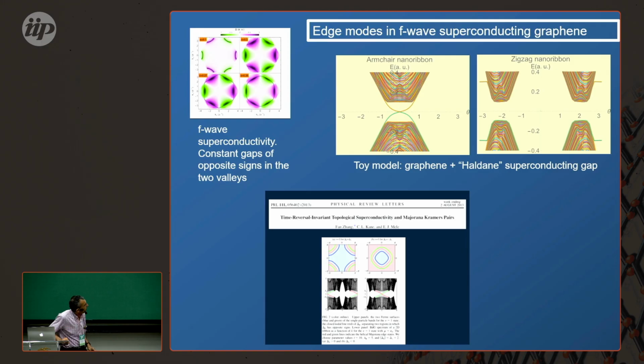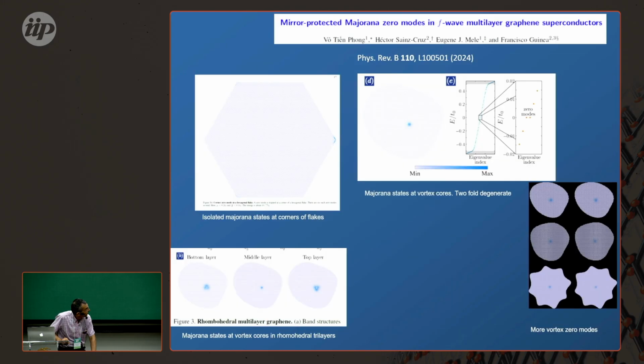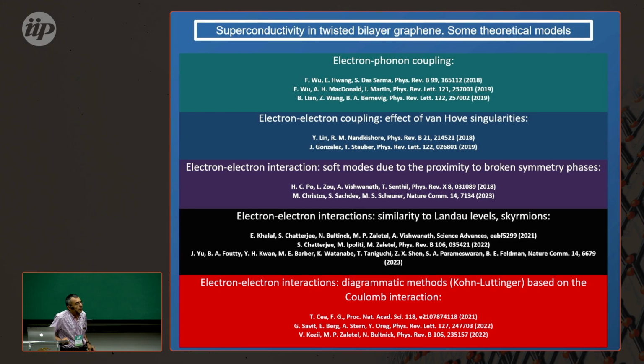They are Majoranas, related to a famous paper by Charlie Kane and Gene Mele on edge states protected by crystal symmetries. They were not originally considering superconductivity, but you can have these Majorana states in different configurations, typically at armchair boundaries, which are the ones that allow you to mix the two valleys that have different signs for the order parameter.